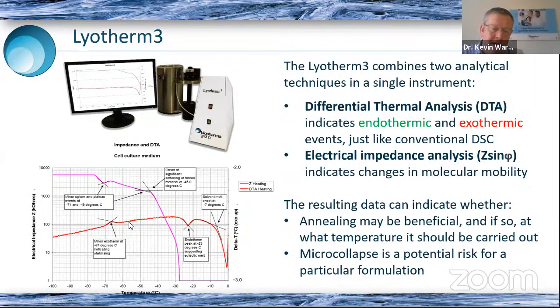But in DTA thermal analysis, we didn't really see any other major thermal events until we got to around -23. Well, we know that there's sodium chloride in cell culture medium, and we know that that melts around -21, but in this case, it's going to happen slightly earlier because we have other things in our formulation. But we didn't really see anything else. And so the impedance line, the change at -45, gave us an indication of mobility changes which were not able to be picked up in DTA or indeed in this case in DSC.